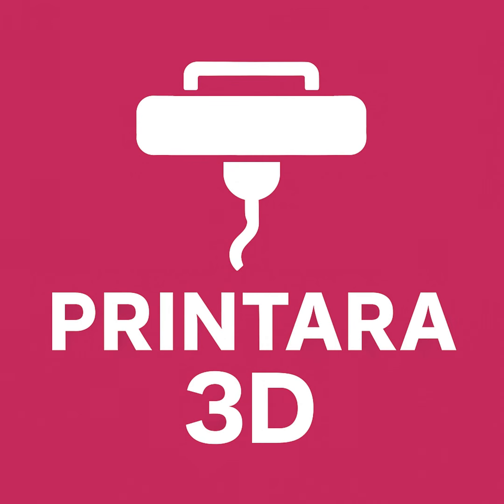So first step is? Dry your filament. Always the first thing to check. If it's dry, then you look at your retraction settings in the slicer software. You might need to increase the retraction distance, how far it pulls the filament back, or increase the retraction speed, pull it back faster and sharper, maybe tweak the nozzle temp down slightly too.